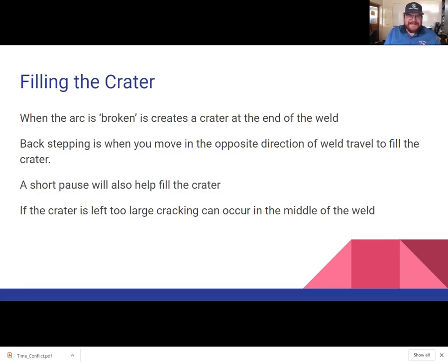What you may see at the end of that weld is cracking in that crater because typically it's going to be a little bit thinner than the rest of the weld, and you might see a crack start to form. If you see any cracks or any holes in the metal, that is a bad thing. We do not want to see that because that crack is then going to fracture the rest of that weld. Think about a chain: the chain is only as strong as its weakest link because every link has to be as strong. A weld is really the same way. If there's a weak spot in that weld, it's going to cause the rest of that weld to fatigue and then fail on us down the road.